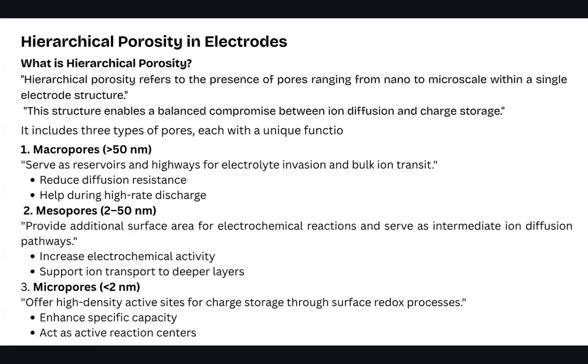Next is hierarchical porosity in the electrodes. Hierarchical porosity refers to the presence of pores ranging from nano to micro scale within a single electrode structure. This includes three types of pores. The first one is macropores, which are greater than 50 nanometers in size. These serve as a reservoir and highways for electrolyte invasion and bulk ion transit. This reduces diffusion resistance and helps during high-rate discharge.